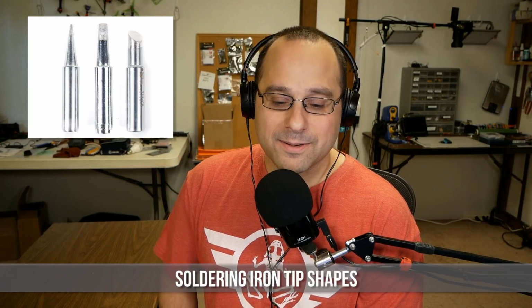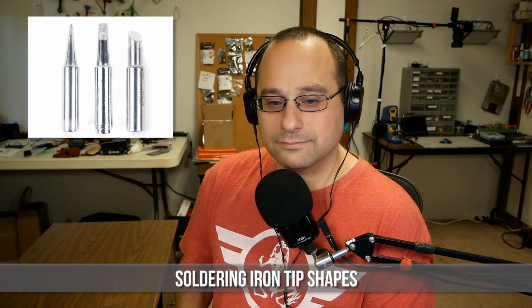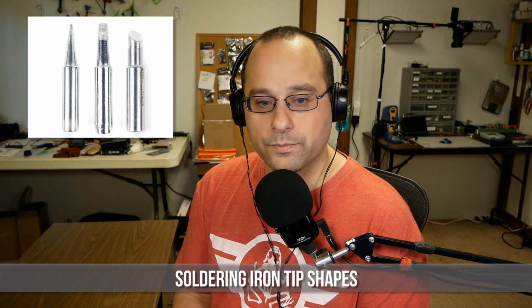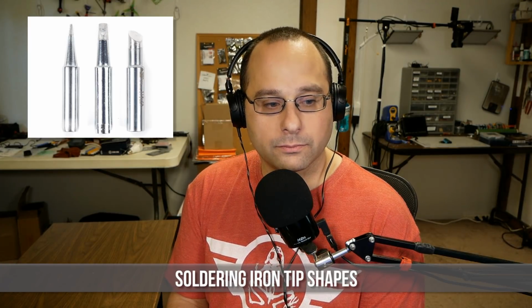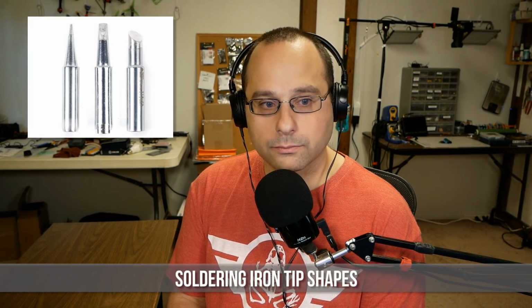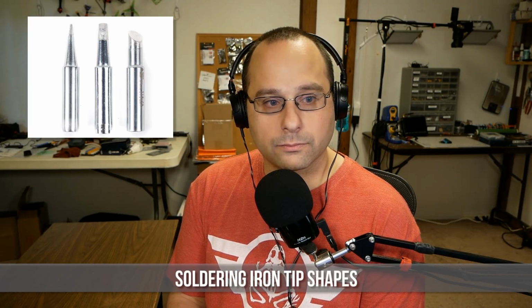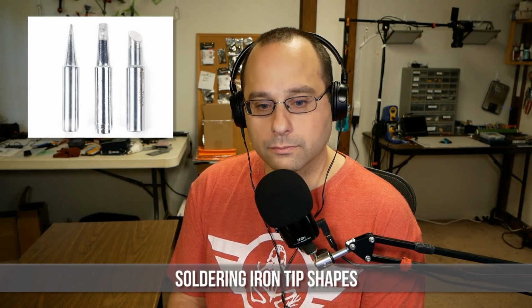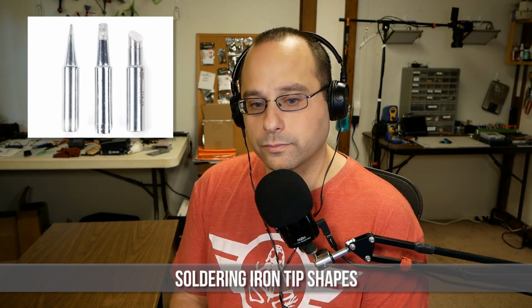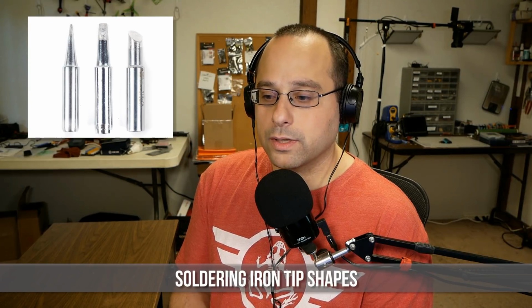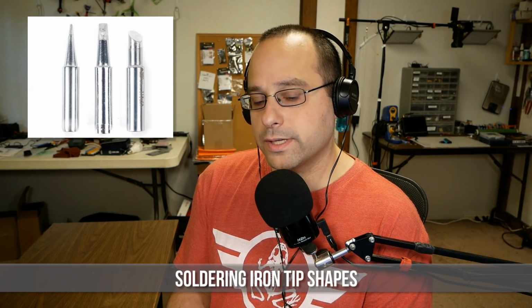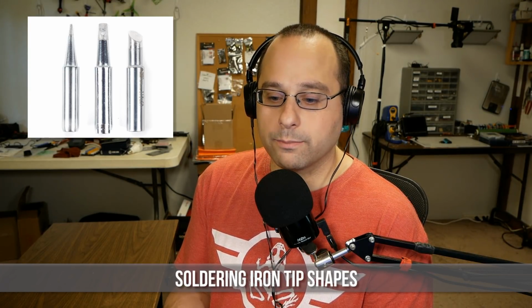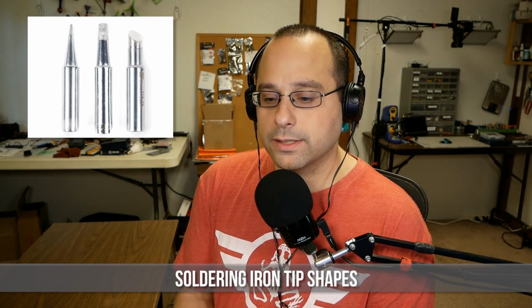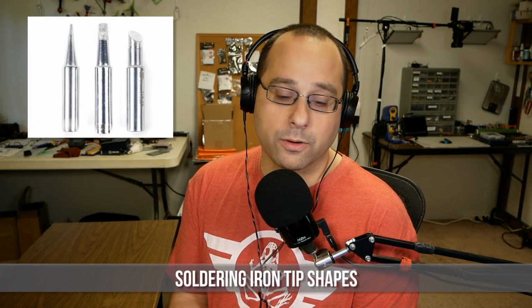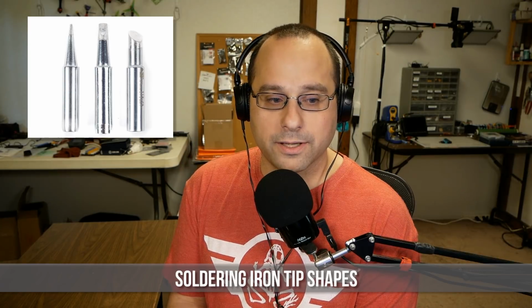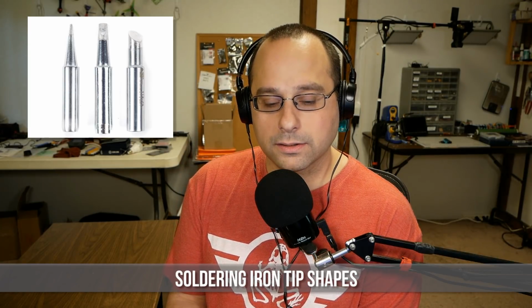Right, and that gets to recovery time, which we mentioned before. As you're putting the tip on some wires, the heat is going to be drawn away from the iron, and a low wattage iron takes a long time to recover to the temperature that you set it to. Yeah. And then the downside, I think, of the bevel tip is, like you say, they have more surface area. So especially in tight environments, you're more likely to accidentally damage something or get the heat where you don't want it. Right.